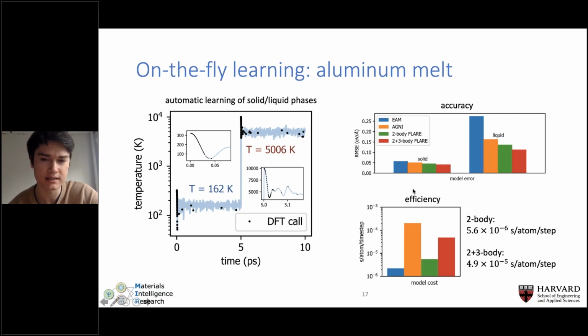Equally important for us is that we were able to get a very efficient model after mapping the Gaussian process to cubic splines. Because we're making this assumption that the potential energy surface breaks into these 2 and 3 body terms, we can map those low dimensional terms directly, implemented in LAMMPS, and get potentials that are quite competitive. You can see our 2-body model shown in green here is roughly the same order of magnitude as the EAM potential. 2 plus 3 is about an order of magnitude slower than 2-body, but still in quite a reasonable range where you can handle fairly long simulations and big system sizes.